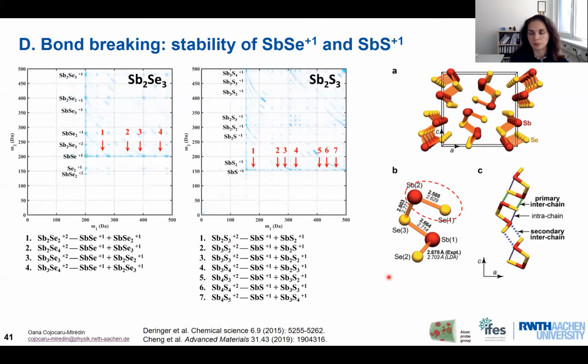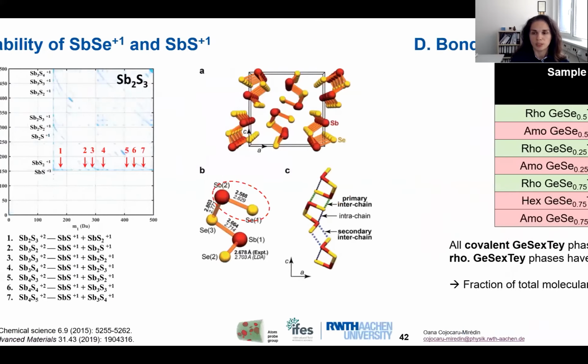To have a clearer map, I show you here some DFT calculations done on antimony selenide. It was found that we have indeed 4 different bonding lengths in antimony selenide. Three of them have longer bonding lengths and only 1 has a very short bonding length. And this might be the reason, because we know that the shorter the bonding length, the stronger the bonding at the end. Then this might be a reason why we end up having very stable molecules during the dissociation in the atom probe experiments.